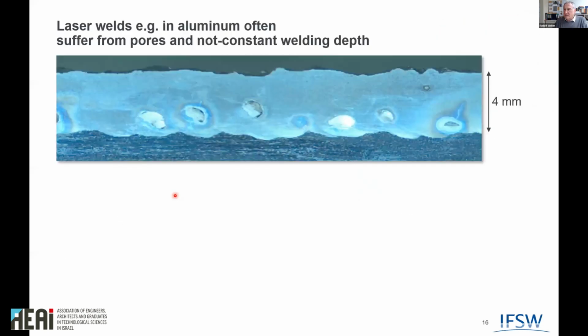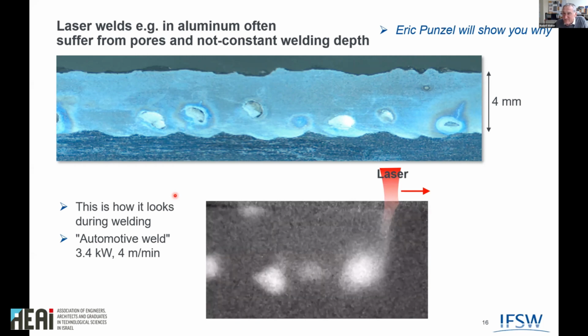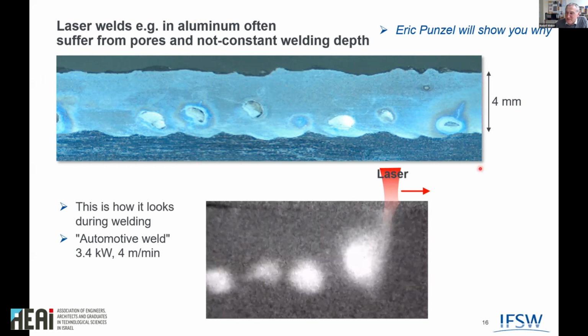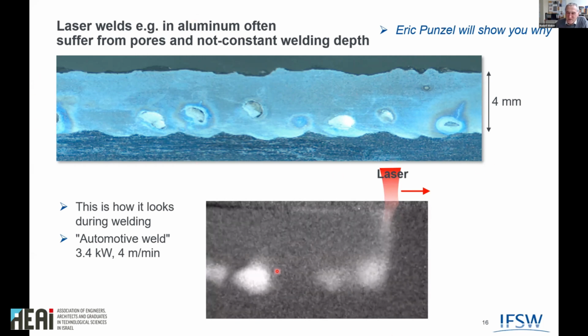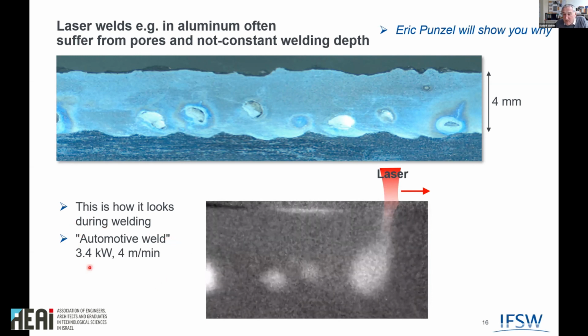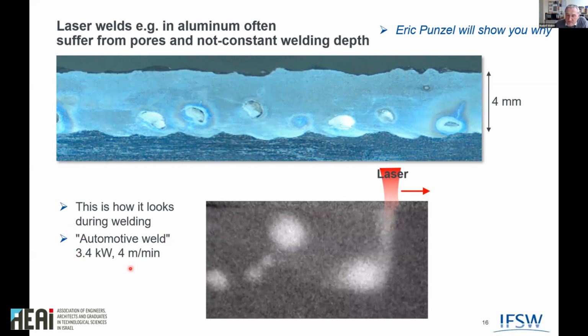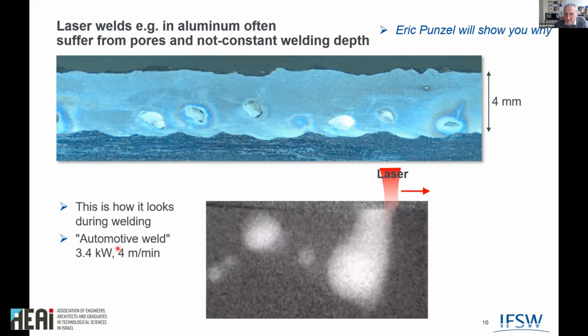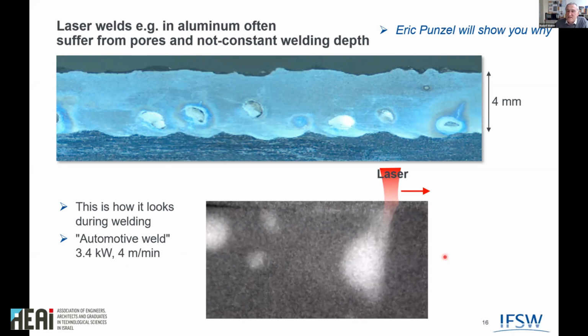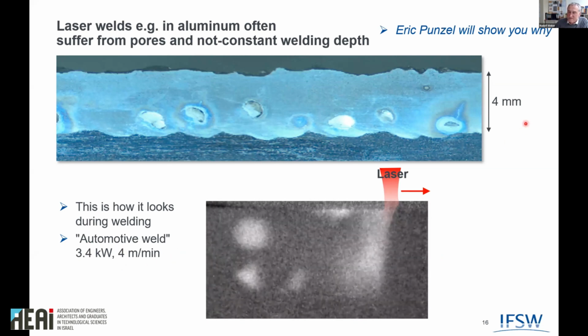And the last thing I would like to show you, only because it's nice. We also had a lot of pores, and Eric Punzel will explain everything about pores in his talk after myself. But I have a film which he does not have. That's how it looks inside such a weld, by the way. You create a lot of pores. This is typical automotive weld parameters, 3.4 kilowatt, 4 meters per minute. So that's how it looks. You also see that it's not very constant.